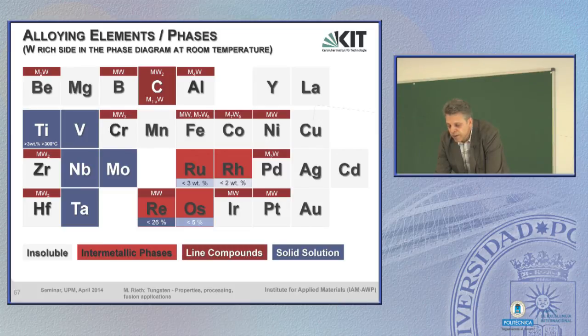Now if we have a look at the periodic table, insoluble elements are in white. The intermetallic phase formers with tungsten are in red. These are very specific intermetallic phases, line compounds, they are in dark red. And what remains for solid solution is only titanium, vanadium, niobium, molybdenum, and tantalum. And to a small amount, as we have also mentioned, rhenium, and even less, osmium, ruthenium, and rhodium.